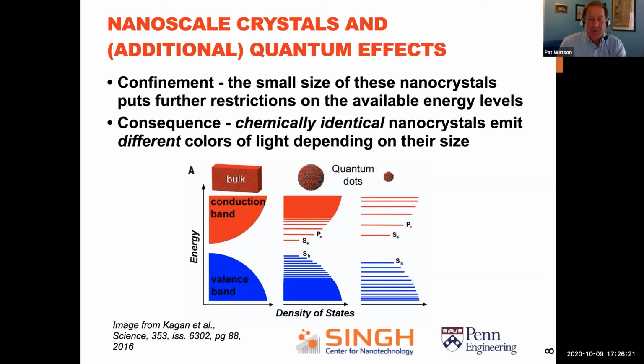If we make that bulk material into a quantum dot, like the middle one there, then this confinement forces these things into discrete little states. And the distance now between that SE and the SH is a little larger than the bulk material. So it's going to higher energy, and it's going to give a bluer light when it emits light from photoluminescence. And then if you make a super tiny one, like the rightmost one, that gap gets even larger, and the light gets bluer. So the cool thing about this is that we don't change the chemistry. It's exactly the same material, cadmium and selenium, equal amounts, but the size of the structure determines what the color is that's going to be coming out of them.